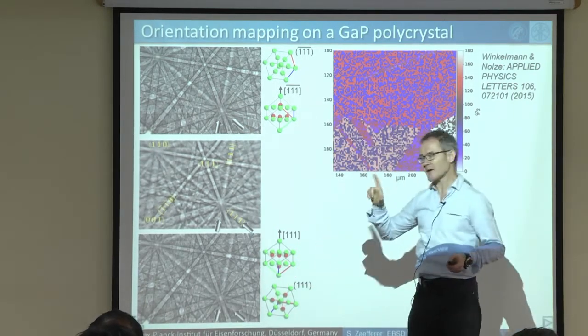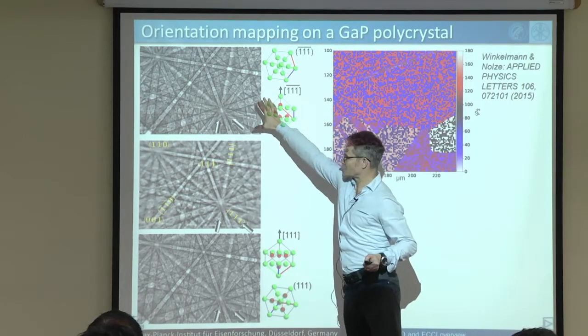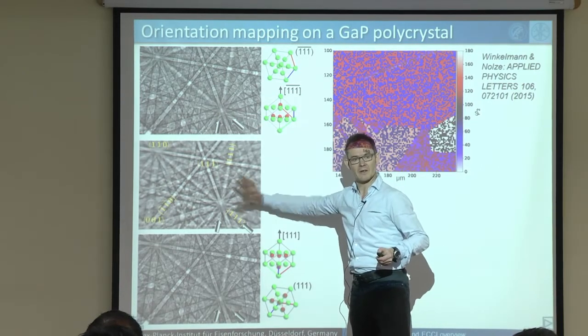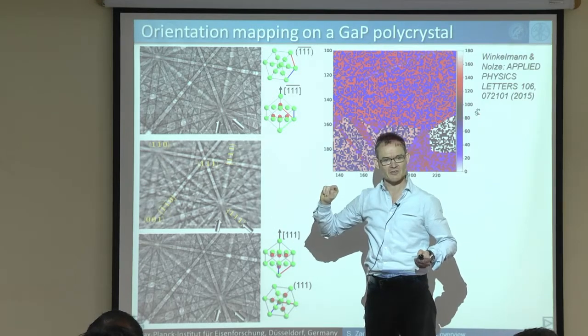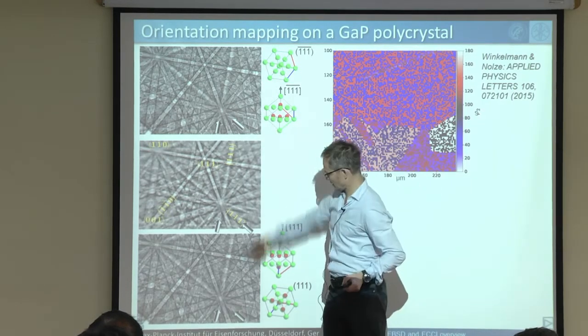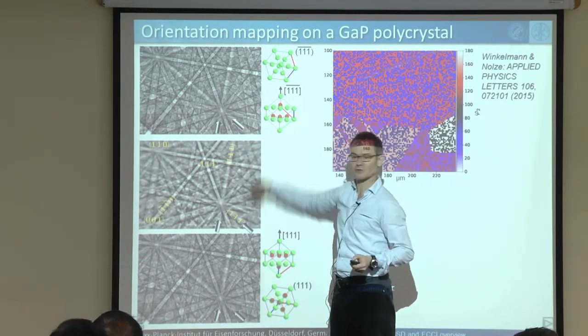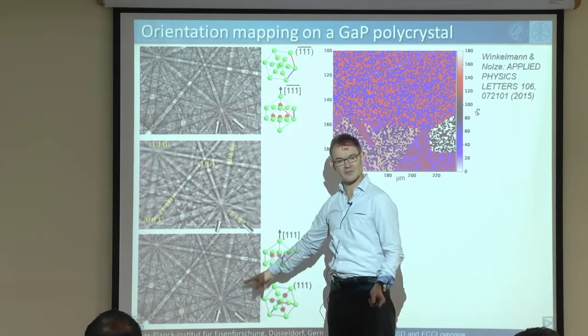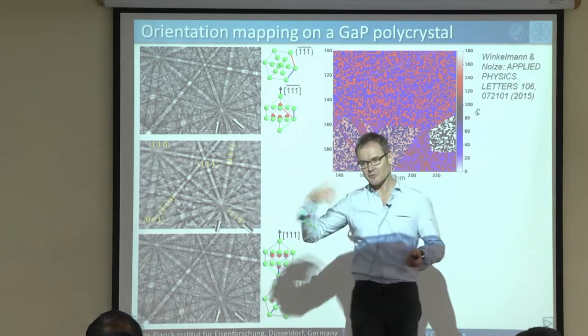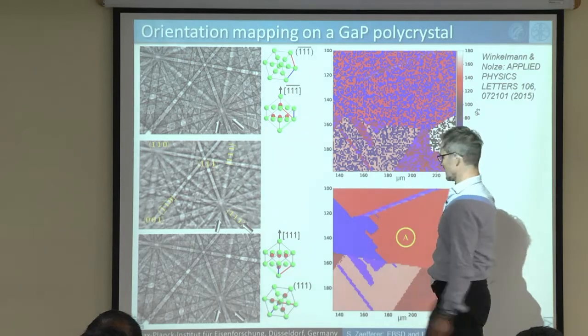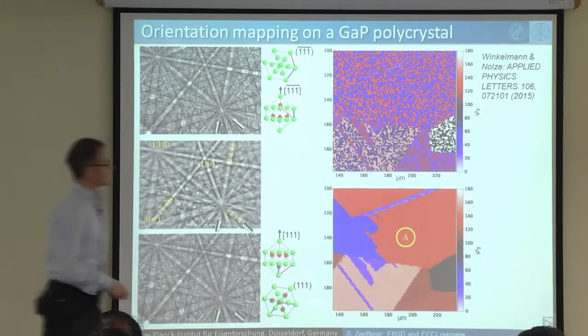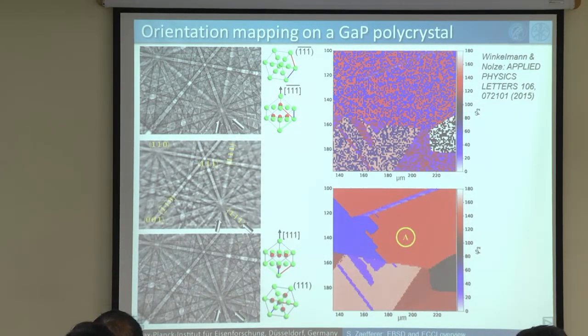And now the software actually calculates these diffraction patterns and compares them with this one, pixel by pixel, intensity by intensity, and figures out that this one here fits better to this than this one. They both fit, but this one fits in intensity better. And the software does this now for every point, and then as a result, it is able to suddenly show the microstructure correctly separated for plus and minus.